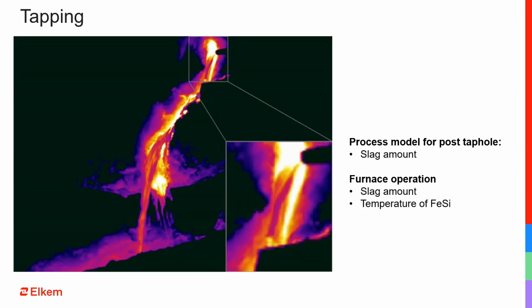A direct view of the tapping hole of a ferrosilicon furnace is usually obstructed by large amounts of smoke, hot gases, and extremely bright light from the high temperature metal. As seen from this brief extract from a video stream, the infrared camera allows for easy observation of the metal stream from the tap hole. Elkem has developed algorithms for identifying slag and metal from a video stream as shown here. In the example, slag droplets in the stream are shown in a green color to aid the eye. The main output is the amount of slag measured in kilograms per tap. In addition, the infrared camera gives a continuous temperature measurement that is very useful for understanding the overall furnace operation.